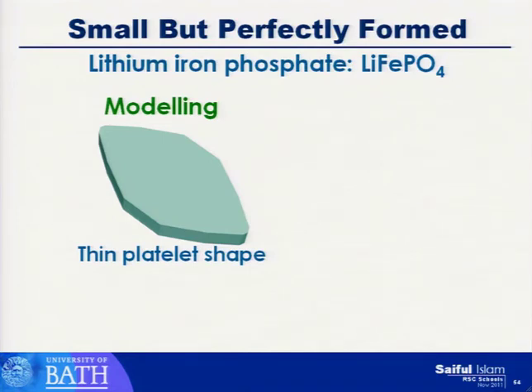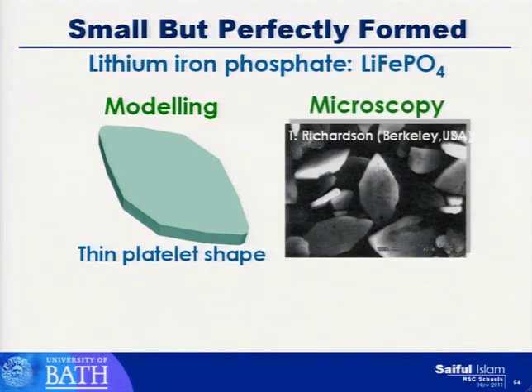And from modeling, we find this kind of, instead of needle-like shapes, a very plate-like shape. And that produces this thin plate-like shape from modeling. And what was nice is, from a collaboration with a guy called Tom Richardson in Berkeley in the USA, he synthesized these very plate-like crystals. So we helped him actually identify the different surfaces within his crystals. But why is that important?